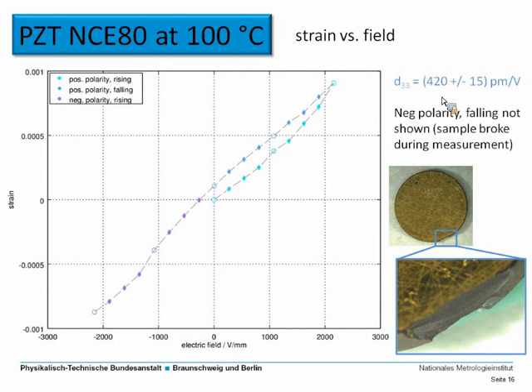And now maybe if you're wondering why this part here of the curve is missing, there's a simple explanation: the sample broke during the measurement. You can see it here, that there is a bit actually blown away or chipped off at the edge of the sample, and probably that was some electrical breakdown during the measurement, and because of some high strain developed during that process, it just was blown away.